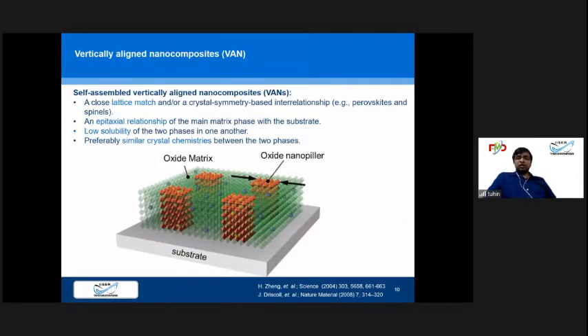So we came up with another solution, which we call a vertically aligned nanocomposite. In this, we also deposit the materials epitaxially, but instead of depositing only a single material, we can deposit two different materials at the same time. So one material forms a matrix, which is, let's say, the green color here. And within that green matrix, we have a column structure of a secondary material. We have to choose the materials very carefully so that they do not mix with each other, otherwise we will not get nice looking columns within the matrix. And we have optimized the parameters we need to create such a well-refined structure.